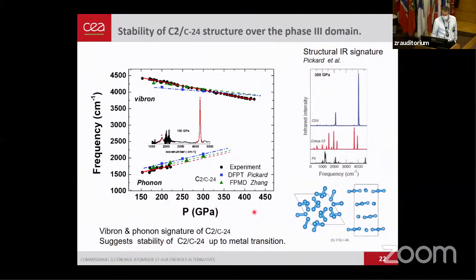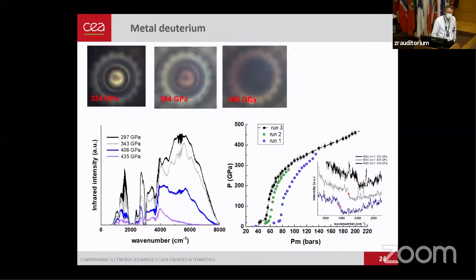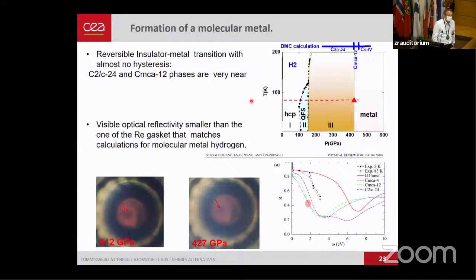The disappearance of the infrared vibron is due to the fact that the gap is completely closed, so there is no light going through the sample. The disappearance of this vibron is a consequence of the metallization, the fact that there is no transmission in infrared anymore. The gap is closed. For the Raman, you can measure the Raman until the visible gap is above your Raman signal, and we could measure the Raman of D2 up to, I didn't show that, 320 GPa, but then the gap was closed and we could measure nothing. So the disappearance of the Raman vibron or infrared vibron is no evidence at all of metallization. It's a consequence of the decrease of the gap.